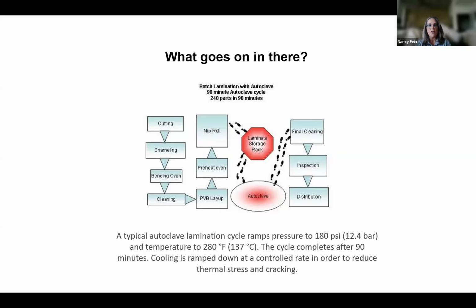So a typical autoclave lamination cycle pressure is up to 180 pounds per square inch, which is 12.4 bar, and the temperature is up to 280 Fahrenheit or 137 Celsius. And as I said, the cycle completes in 90 minutes, and then the cooling is ramped down at a controlled rate to prevent the glass from failing. You don't want it to cool too quickly.